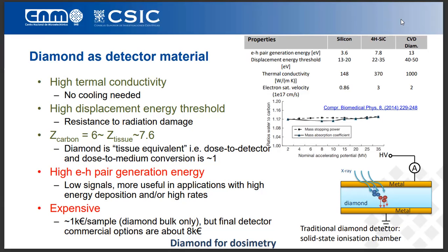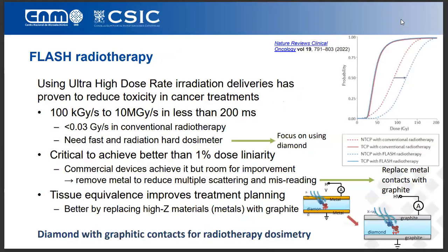So the idea again is to use diamond as material for dosimetry, in particular for flash radiotherapy. This is a relatively new way of radiotherapy. It benefits from using ultra high dose rate deliveries, which have been proven to reduce the toxicity in cancer treatments, meaning it affects more the cancerous tissue than the healthy tissue. But the problem is the ultra high dose rate is very high: high doses in a very short time, even less than 200 milliseconds. And there you have the reference from conventional radiotherapy.